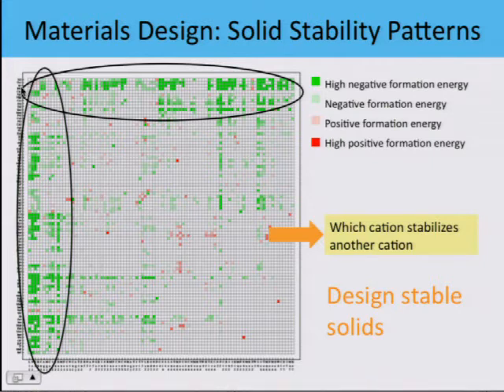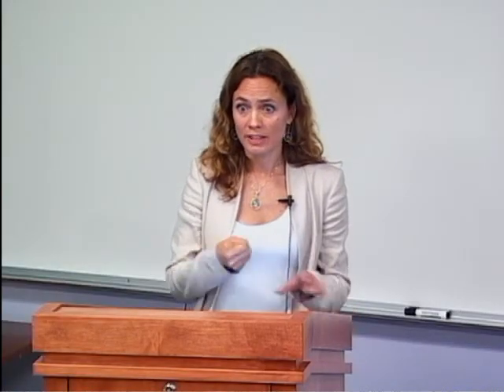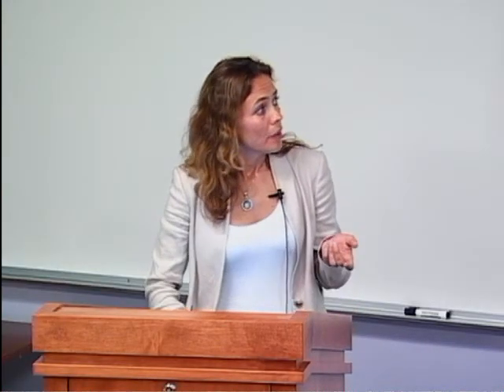So here, let's say you have lithium together with manganese 6+, and that may have a green dot because they really like each other in oxide environments. One of the things we found out by this data mining was how to stabilize those high valent cations that you need for high energy density. You need things like nickel 4+, cobalt 4+, manganese 6+ to be able to take up a lot of electrons. And that's the way you get energy density, right? But it's hard to stabilize them.